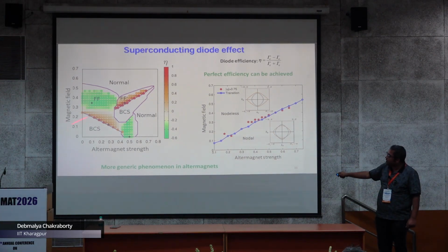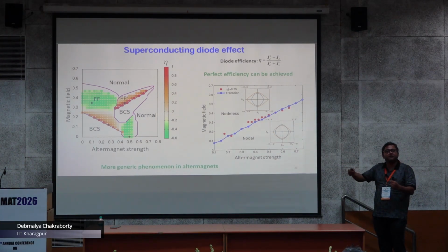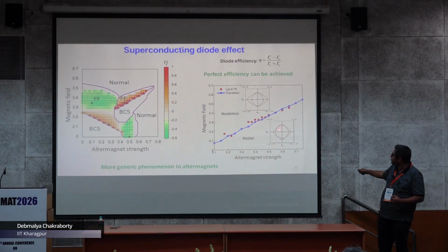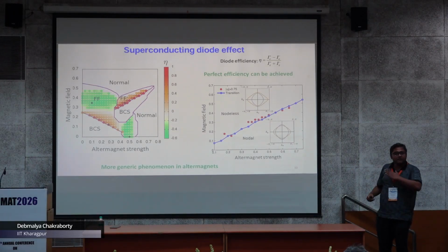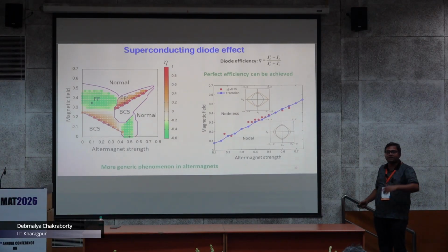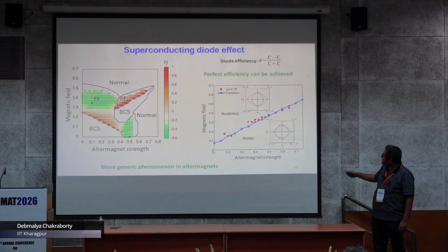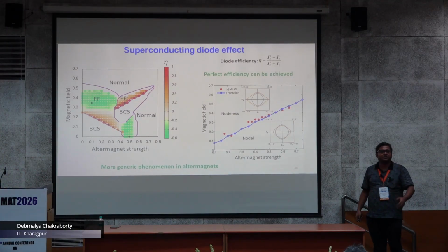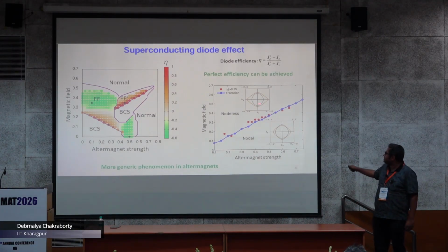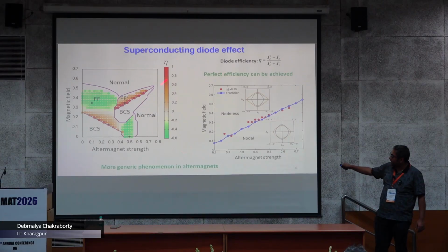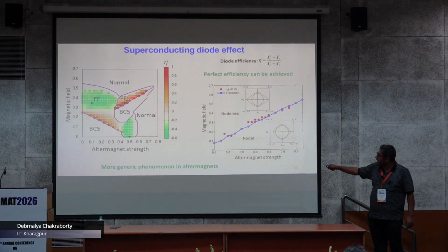So there is a topological transition of the Fermi surface. That means it goes from these 4 nodes to no nodes, and this blue line indicates the transition from nodal to nodeless. And these red points are the points where efficiency is extremely high, and you see that they actually lie on this line. So it will be high here and here.